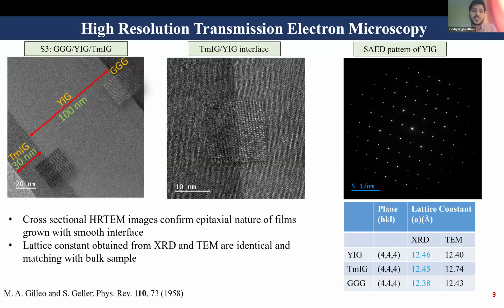From the cross-sectional TEM images of these samples, we can characterize the thickness of the TMIG thin film as 30 nanometers, YIG as 100 nanometers, and the substrate that you can see here. A good, sharp interface is also clear from these cross-sectional images. The diffraction pattern also tells us the epitaxial nature of these thin films, and from the calculation of the lattice constants, the XRD and TEM also confirm that the thin films are well grown and oriented, in agreement with the corresponding literature.